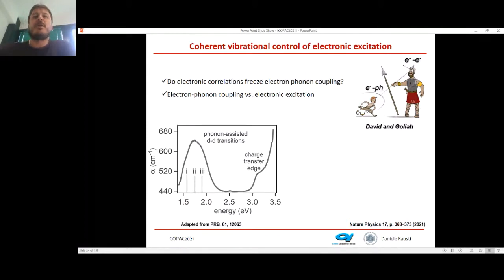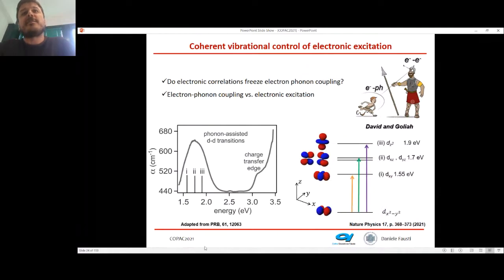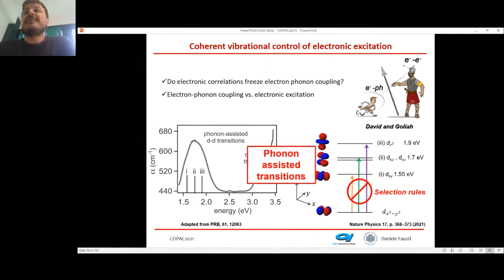The system which we chose to study to prove that this is possible is one of the cuprates, a system characterized by having some specific absorption in the visible, and this absorption is associated with a localized charge redistribution on the copper ions. Those transitions should not be allowed optically, but they are actually allowed because they are phonon-assisted transitions. So it's an optical transition which in principle is forbidden by the dipole selection rule, but it's observed in real measurements. This is because the electronic transition is assisted by a phonon excitation, so the structure breaks the symmetry and makes this transition allowed.